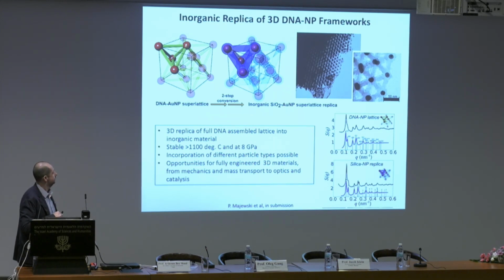We can deliberately silicate DNA only. This allows us to create essentially this 3-dimensional architecture which fully replicates what we made out of DNA. And as you can see by scattering, it's basically almost the same. There is about a 10% difference in the lattice constant.